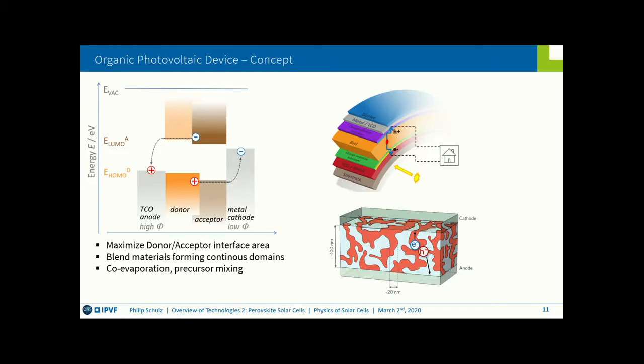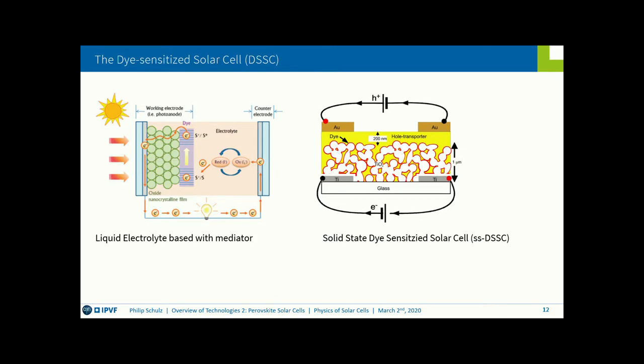Now you can do this by co-evaporation or precursor mixing, but you end up with this kind of scenario here. So in red you have your acceptor, and in blue you have your donor, and you can see that each material arranges to the other electrode, and thus there are recombination pathways. Critical for the development of organic photovoltaics was to look at these interfaces and to make them selective, and it's something that is a recurring theme obviously here for photovoltaics, but particularly also now for perovskite solar cells. With this, of course, encapsulation and stability becomes an issue, but we will not talk about this today.